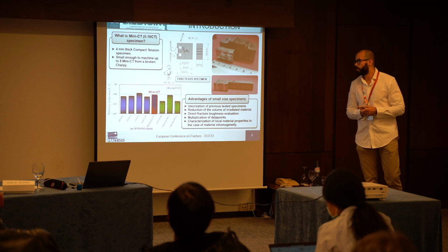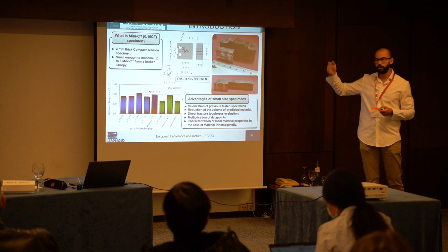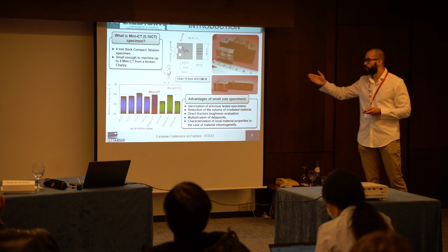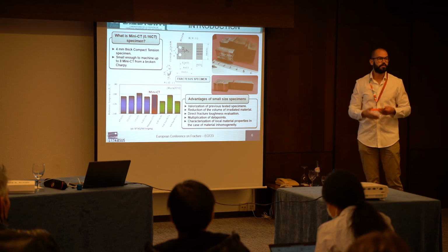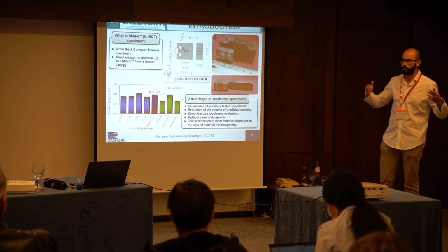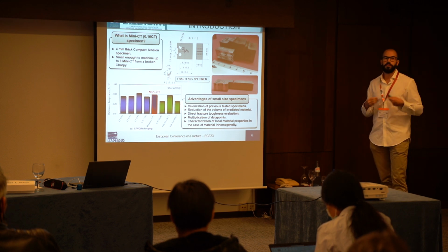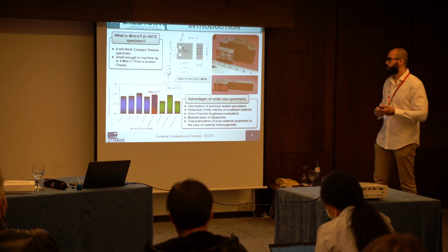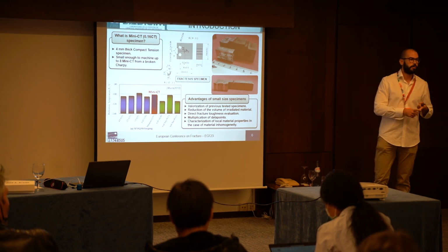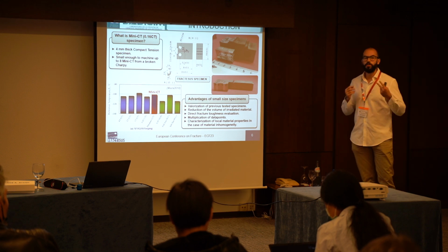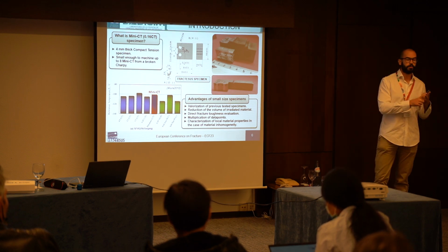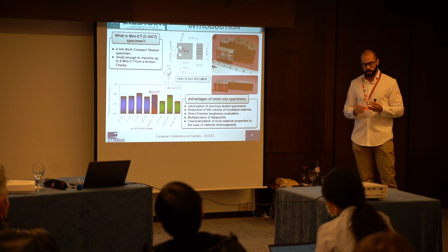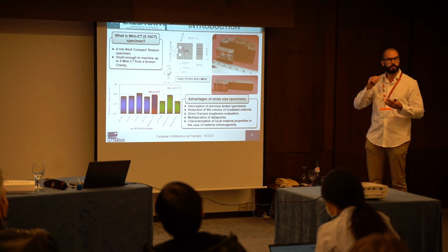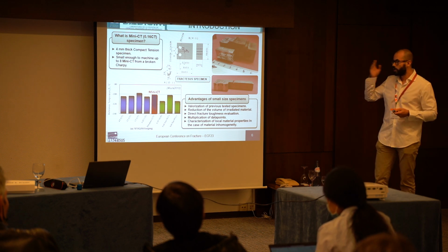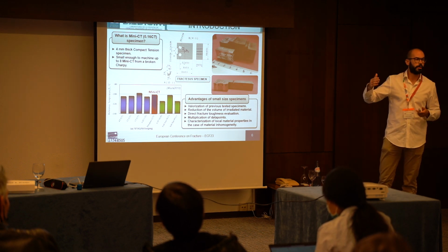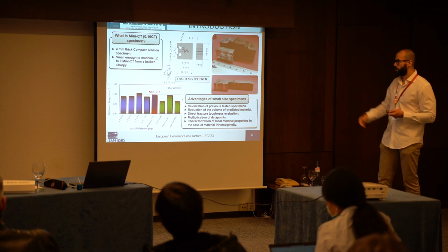This specimen is small enough to machine up to a mini CT specimen from one broken Charpy. This idea has been already validated, for example, by Miura in 2010. He obtained a reference temperature with the mini CT specimen that was in good agreement with larger specimens. So, this mini CT specimen brings us a series of advantages. For example, you can reuse a broken specimen to machine these small ones. You reduce the volume of irradiated material, which is very important. You can increase the surveillance database with direct measurement of fracture toughness. And in case of material inhomogeneity, you can characterize the local material properties.